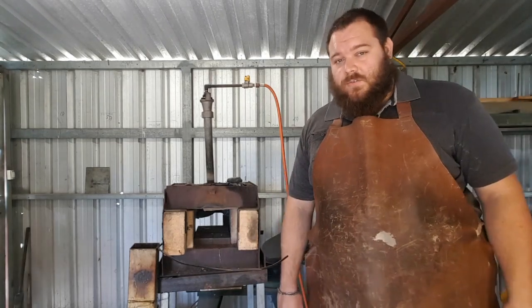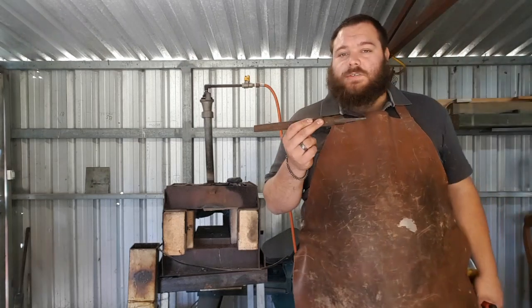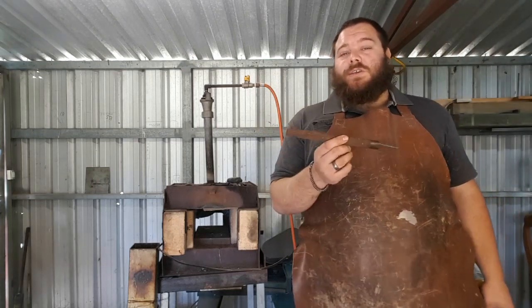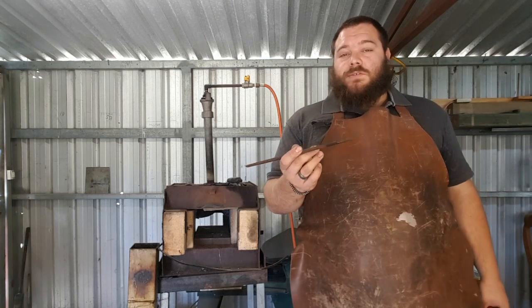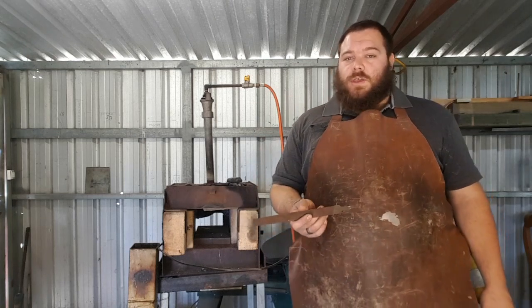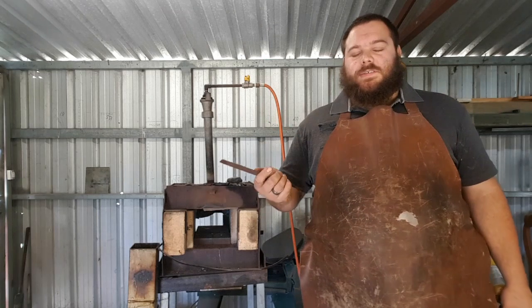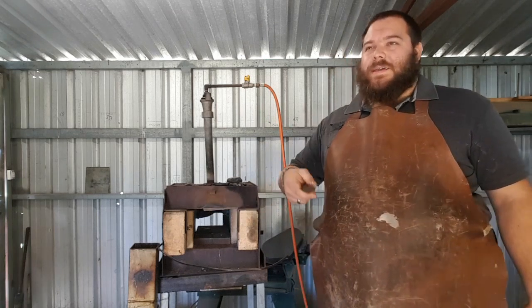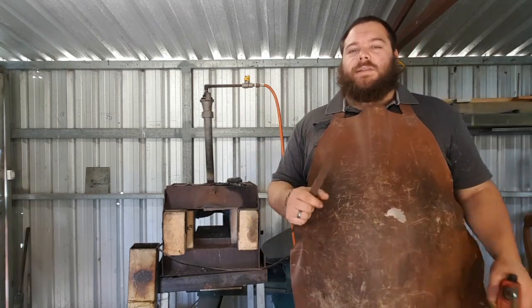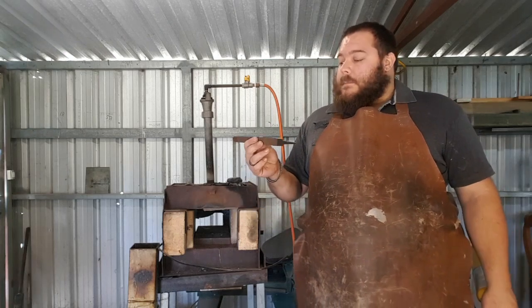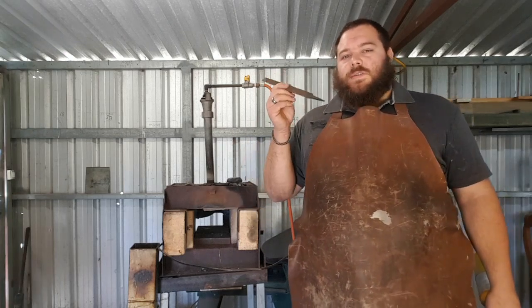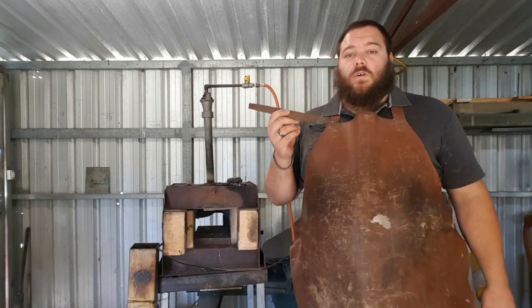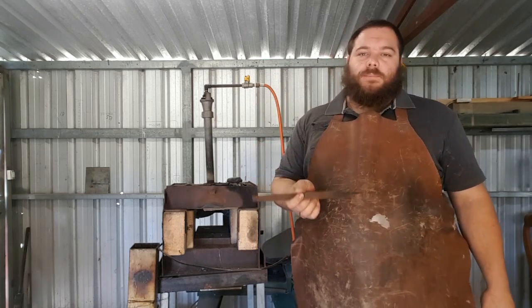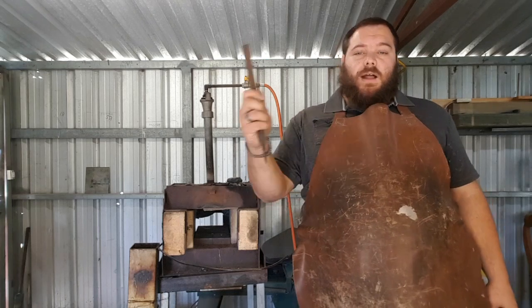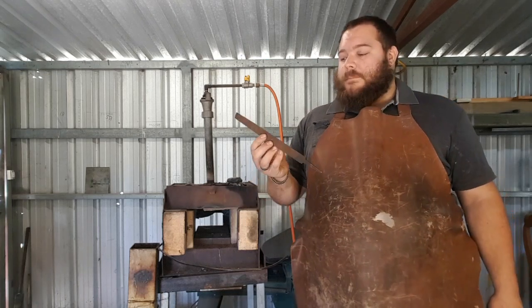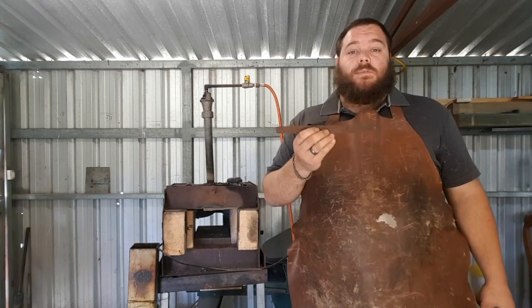The first step of heat treating is to get this to critical temperature and let it cool down, especially when you're using unknown steels or you've forged the material that you're using. Annealed steel that you then stock remove, this step isn't entirely necessary unless you're grinding to the point where you're turning it grey. But with unknown steels, or with steels that have been previously used for something else, or if you've forged it, you have manipulated the grain structure, especially if you've heated it up and cooled it down multiple times. The grain inside the steel is going to be very large.